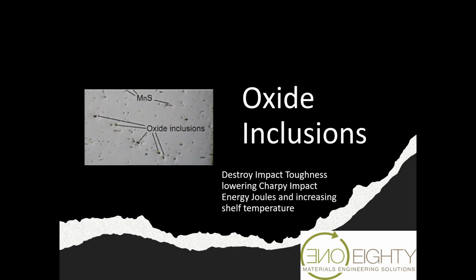And this is what oxide inclusions and manganese sulfide inclusions look like under the microscope. So if you look at the image on the left-hand side, this would be considered a very dirty steel. Just definitely not what you want to see. In fact, we have a mass at the moment of fast brittle fractured components, a large tonnage of them. And this is what they look like. And this is pretty much the reason why they failed catastrophically.